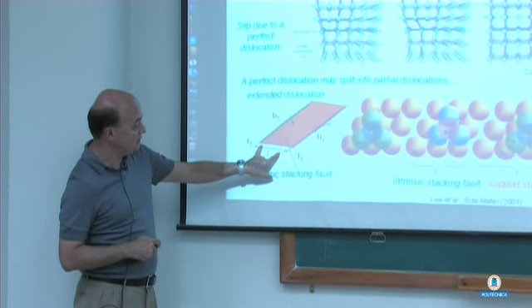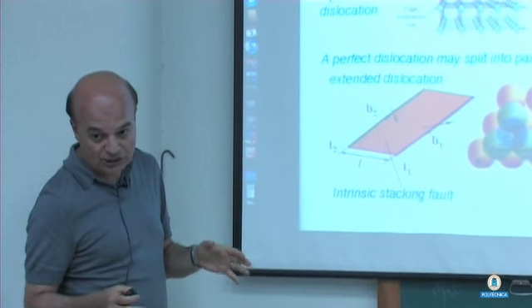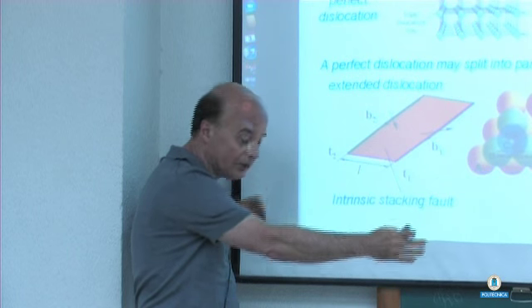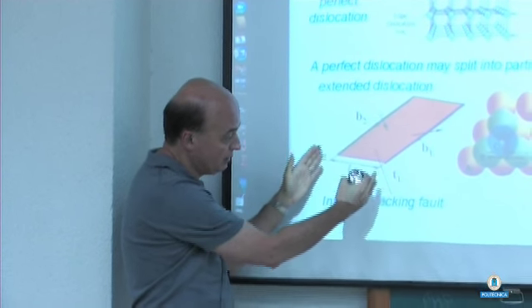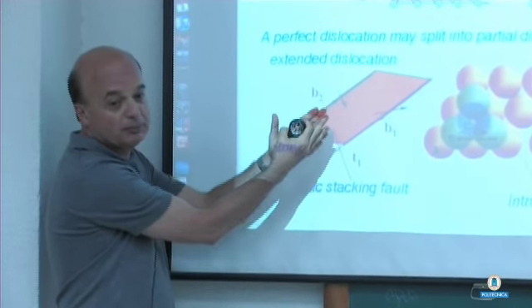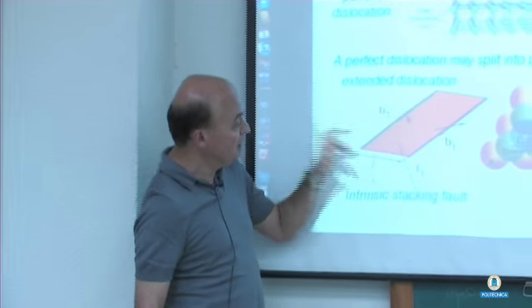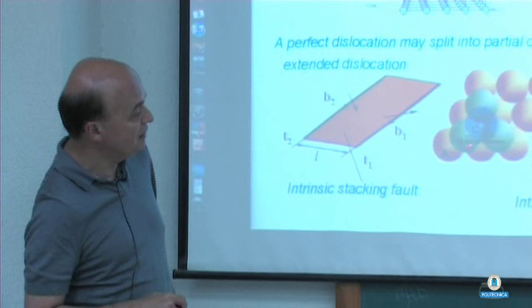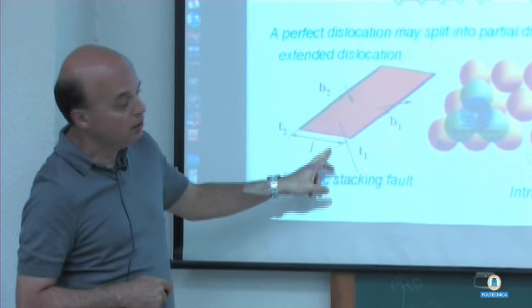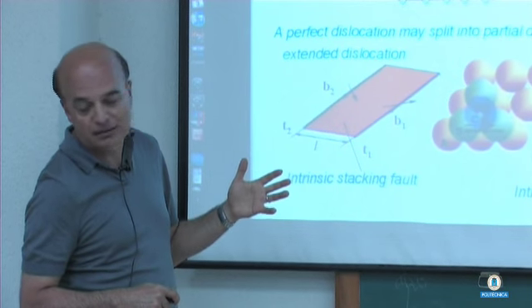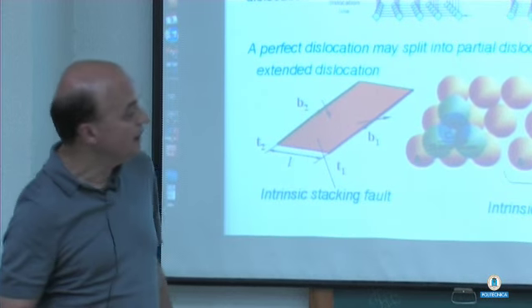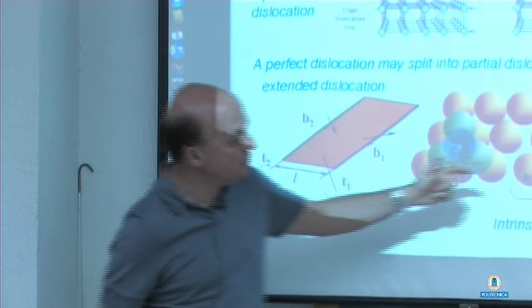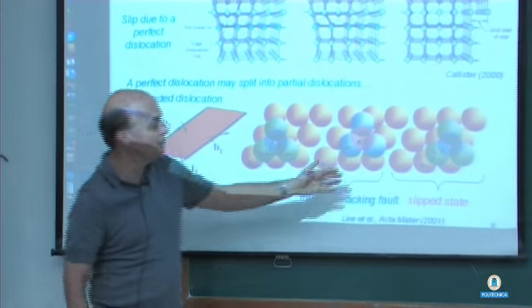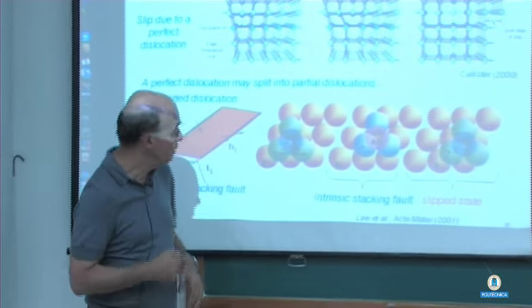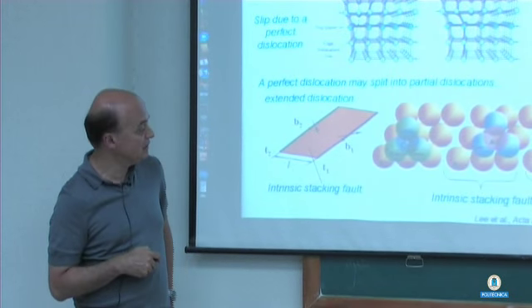That's the stacking fault width. If you have a low stacking fault energy material, that width is pretty wide. If you have a high stacking fault energy material, it's pretty narrow. That way the partials can combine and you can get cross slip. So it's important to note that the FCC stacking is ABC, ABC. Within the fault, the stacking is hexagonal close pack. So in this case it's ACA, and then once the trailing partial passes, you recover. If you look at a material point, you recover in the slip state the ABC stacking again. But within the fault, the stacking is not a face-centered cubic stacking.